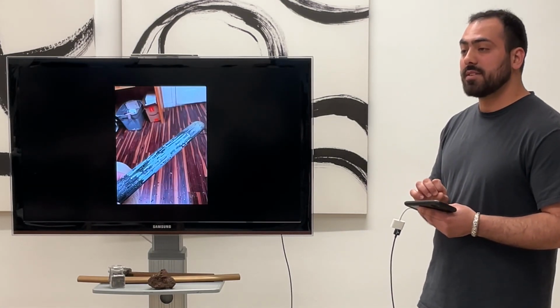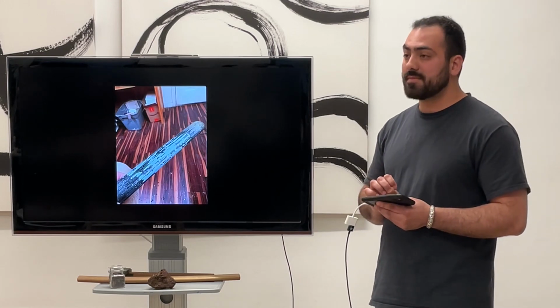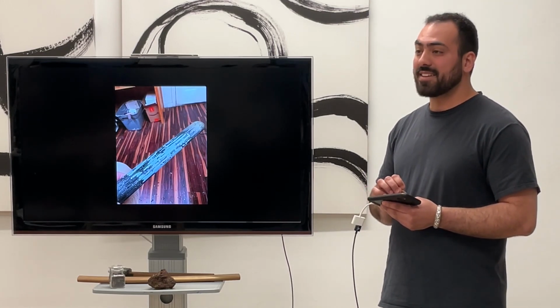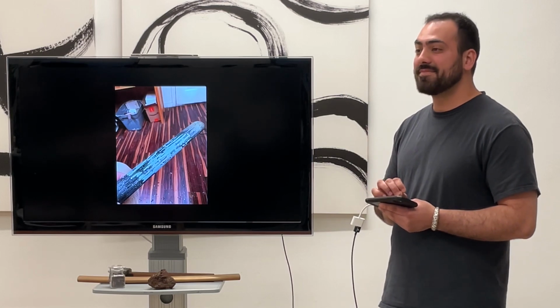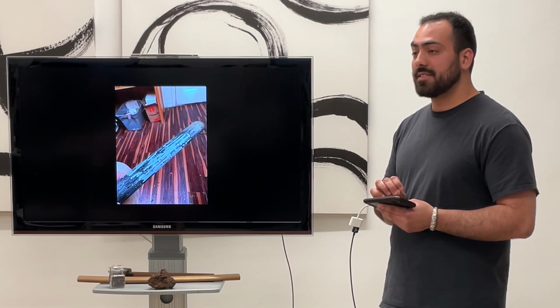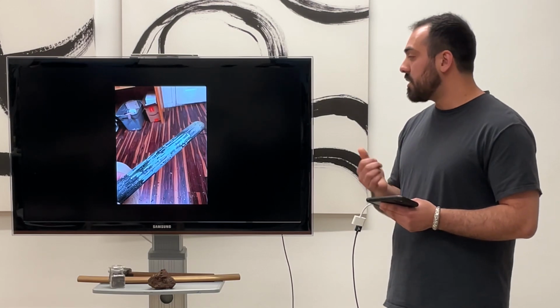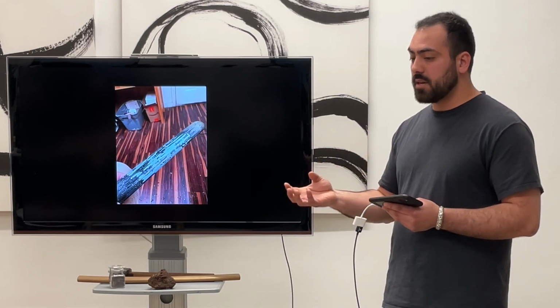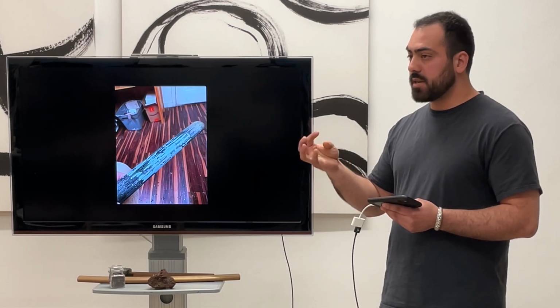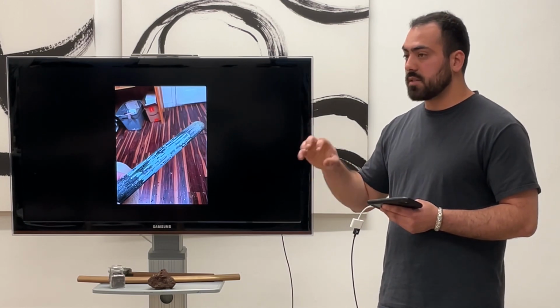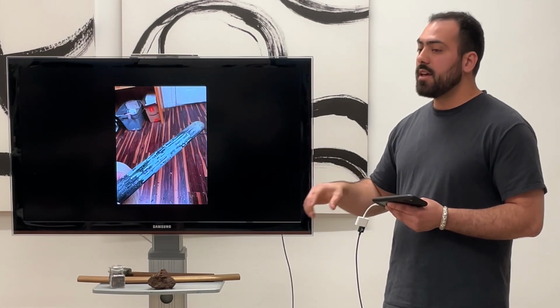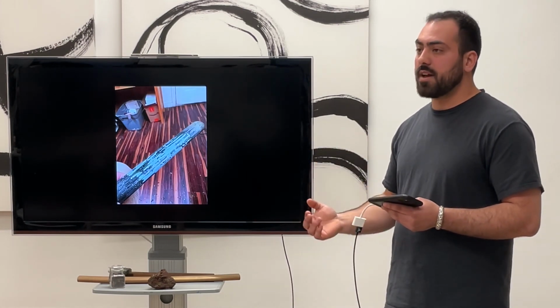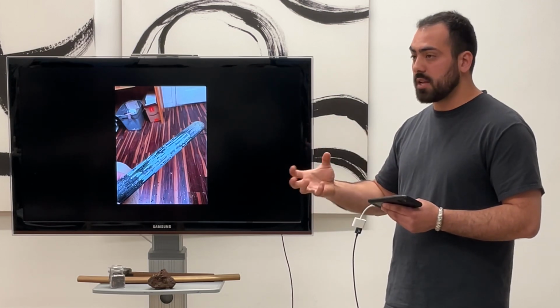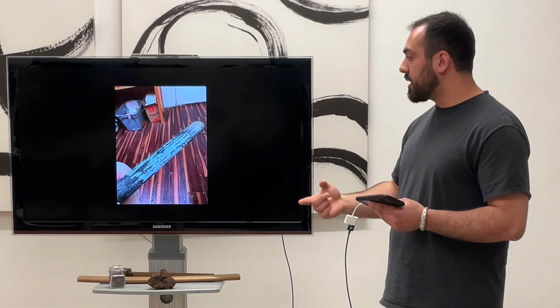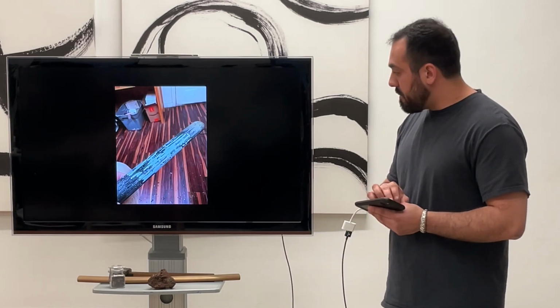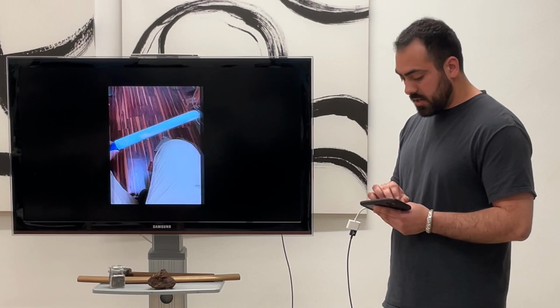Each time you put another layer, you basically dissolve the first one. So when you continue doing this, you're introducing more and more of dissolving things. So the curing is very important. And the issue is mostly that in order for the paint to adhere to itself, it seems like the binder that's in it is supposed to very slightly re-wet the surface underneath it. And not taking that into account, I figured, oh, this is fine. It didn't off-gas enough because it was too cold and it wasn't able to cure as quickly as I needed. So in order to try to get this done, I just ran into trouble. But scrape it all off, start over.